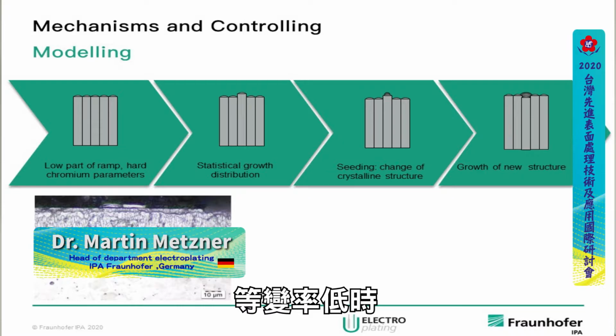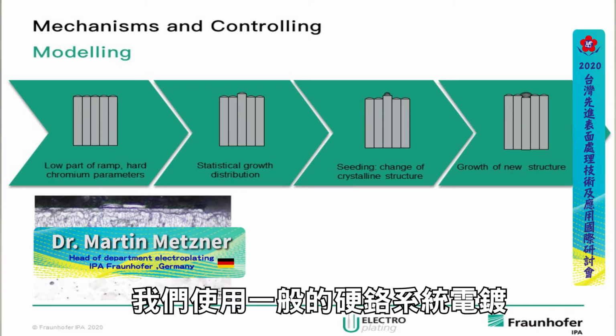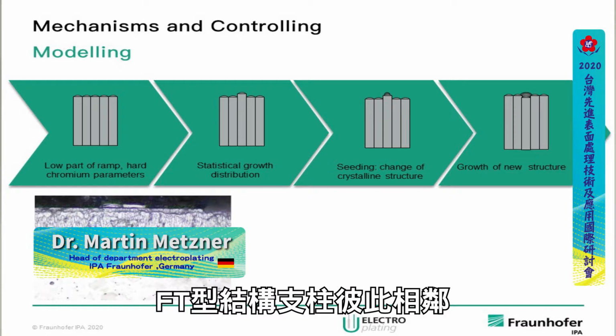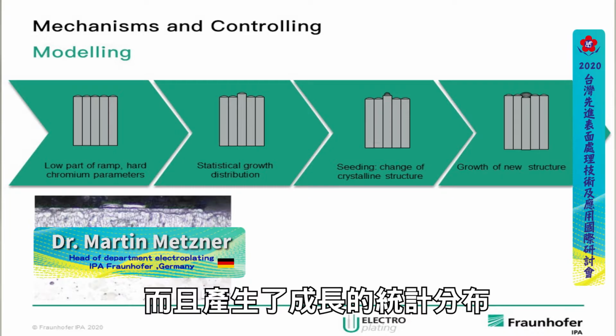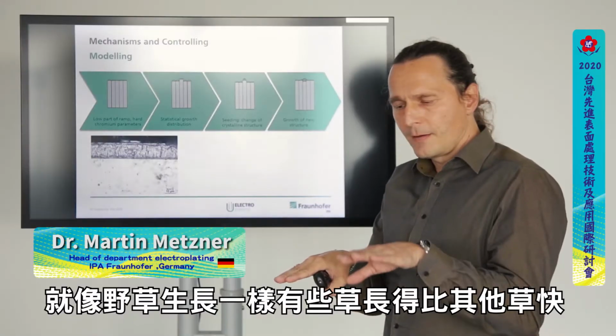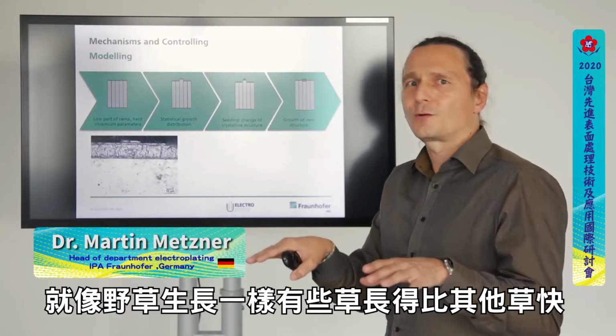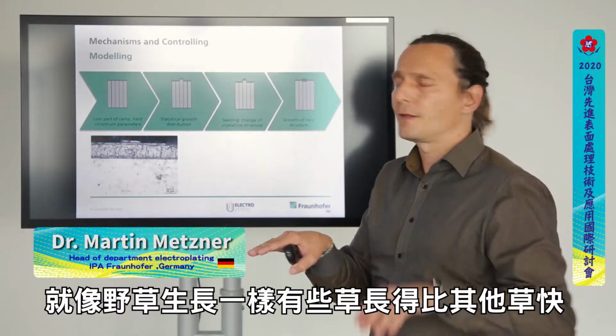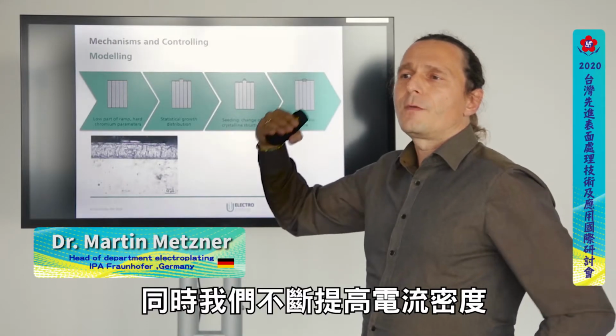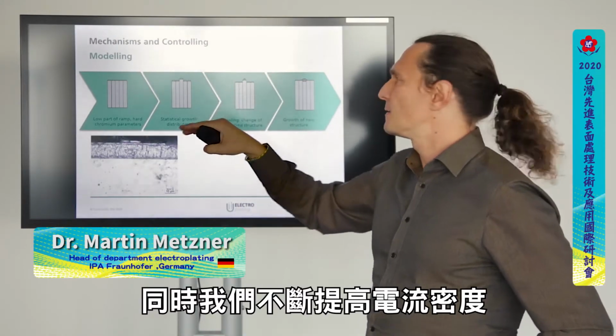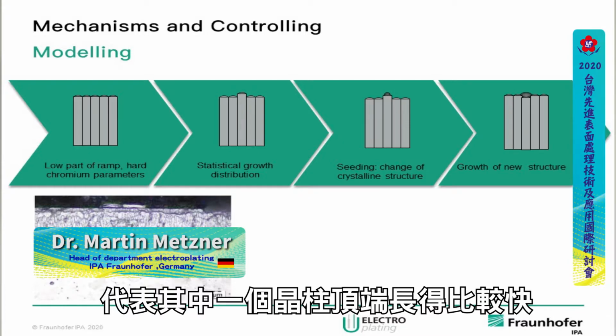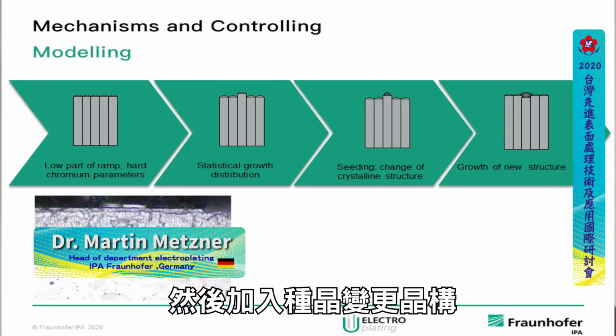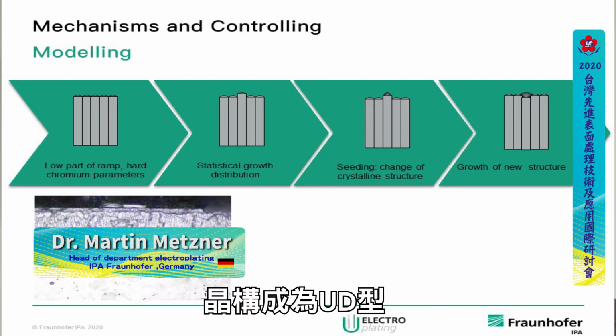When we are in the low part of our ramp, we plate with the normal hard chromium system, field-oriented structure, pillars growing next to each other. And in that, we've got a statistical growth distribution, so it's always like, just when the grass is growing, one is always a little bit faster than the other. And then, at the same time, we rise and rise and rise the current density. And this means on one point, on the top of one of them who's faster, we do the seeding, we change the crystalline structure to the unoriented texture type.